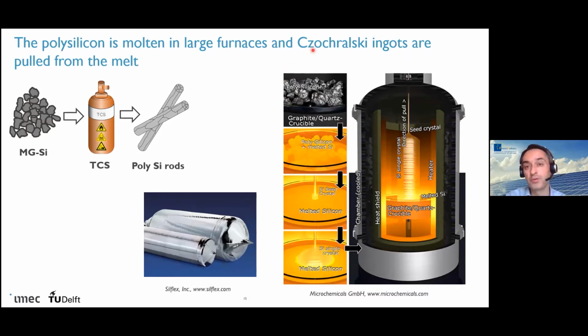And then to make a monocrystalline silicon ingot, we have to start from a small silicon seed crystal, a small piece of monocrystalline silicon with very nice crystalline properties. We put it on top of the melt, and we slowly take it upwards.